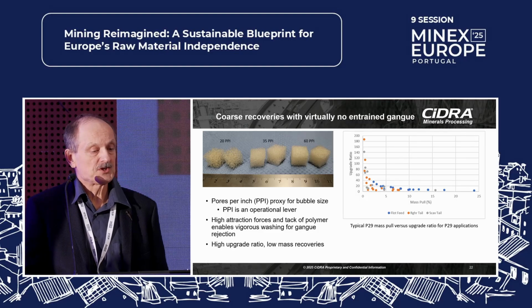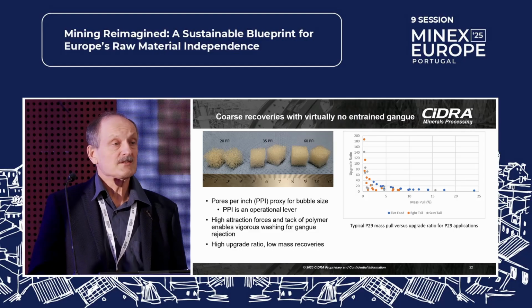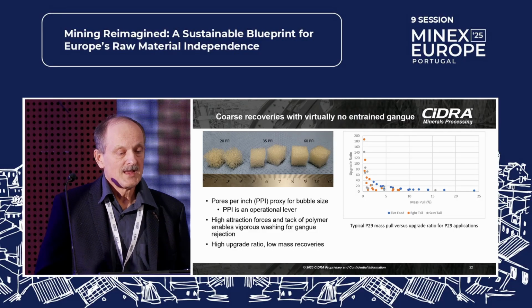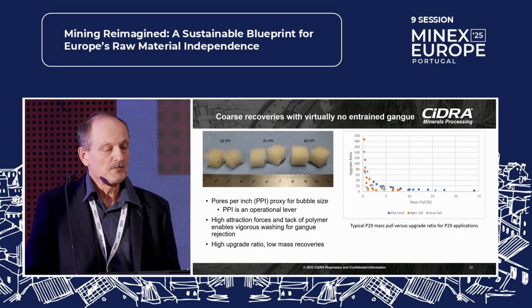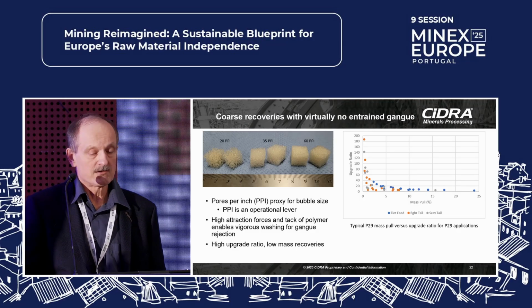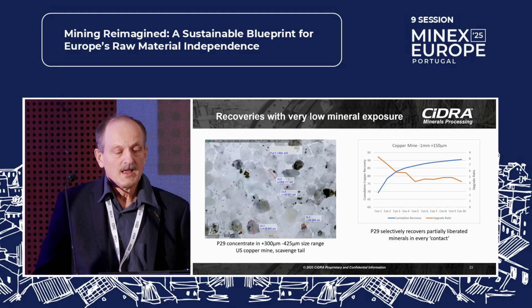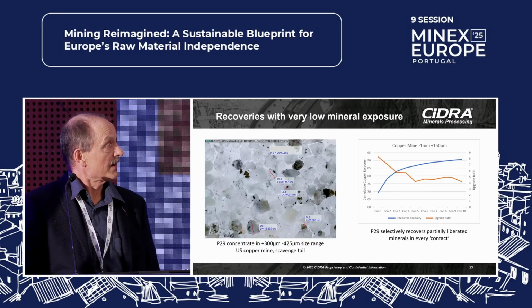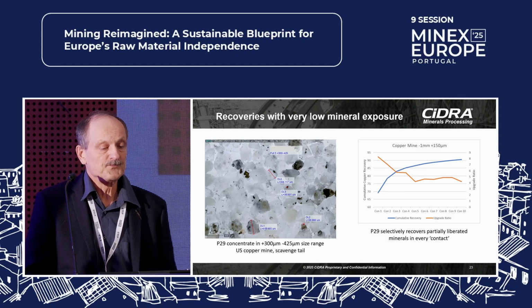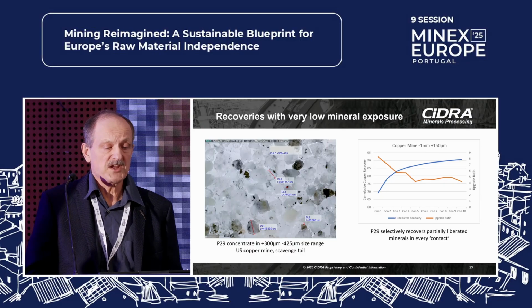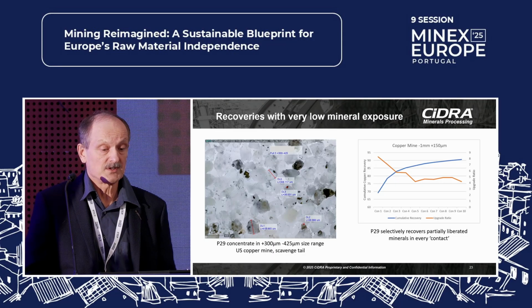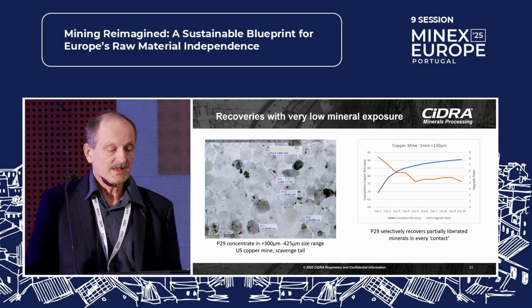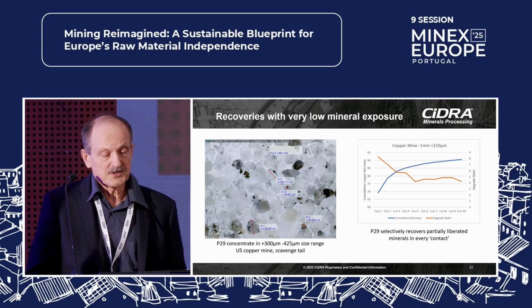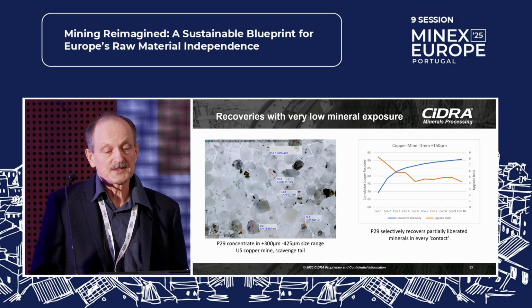The porosity of the sponges will be tuned according to the particle size distribution you want to capture. The high attraction forces and tack of the polymer enables really vigorous washing for gangue rejection at the early stage. So we can capture, here the dark material is the wanted material, so you see that we can capture with very low exposure rates. So less than 1% exposure of the wanted material has to be on the particle for us to capture it. If you compare that to flotation, which is 20 to 25%, that explains why our capture is so efficient at the larger particles.